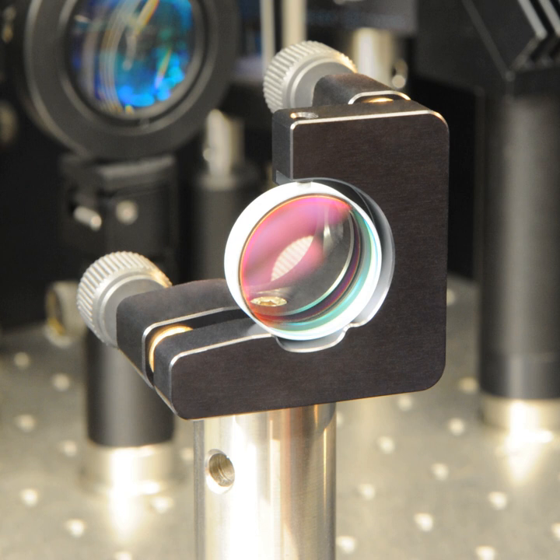Dielectric mirrors function based on the interference of light reflected from the different layers of dielectric stack. This is the same principle used in multi-layer anti-reflection coatings, which are dielectric stacks that have been designed to minimize rather than maximize reflectivity.